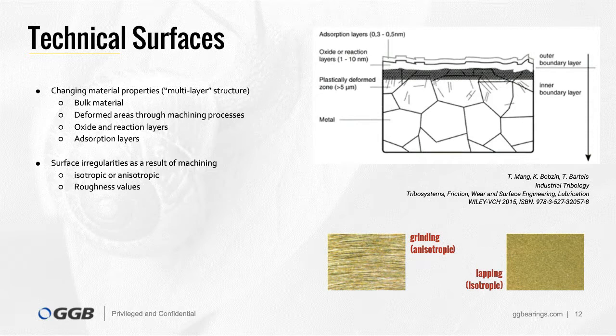On the right side, we see typical images of such topographies, representing typical examples of an isotropic and anisotropic surface. They were generated using two different machining processes. On the right side, we see a lapped surface, and here we see the typical isotropic character, the same in each direction, so we don't have any preferred orientation of the topography. On the left side, we see grinding, which generates a typical oriented structure, which is anisotropic.